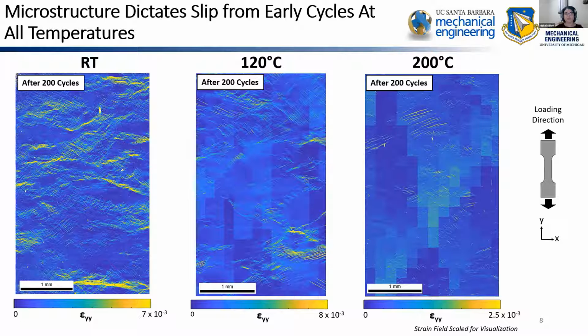Since these were very low strain plastic experiments, it was just significantly easier to see in the Y strain field. But why do you have a Y strain field if it's slip? I mean, slip is shear. What is creating the Y strain? The important thing is that these are just discontinuities. There isn't really a high strain there, right? There's just a discontinuity in the strain field, and so it's expressed as a trace or a line of high strain. Does that make sense?